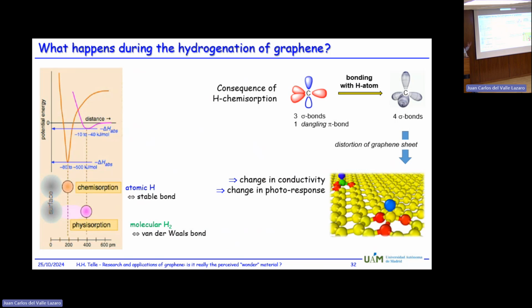So you go from the unperturbed carbon in your graphene to a situation where you now have a hydrogen bonded to it. So the configuration changes from sp2 to sp3. So that is the electronic configuration. But in addition, if you attach the hydrogen, it pulls on your graphene, and therefore you go from the flat surface to one which is distorted. So that changes the properties of the material, and you will see that in the Raman spectra, but you also see it in